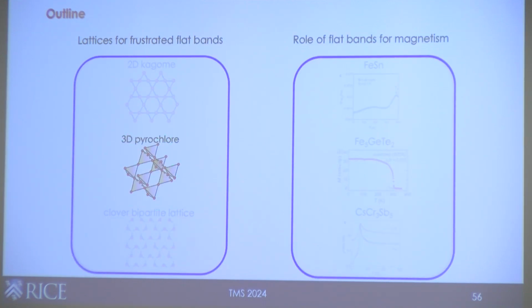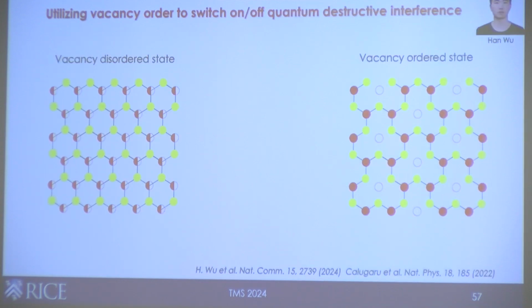So in 3D, we can look at pyrochlore. I want to show you one more that is an interesting and very different way of constructing flat bands in bulk. The difference is that in the previous two examples I showed you, these are fully stoichiometric compounds. You can calculate everything and look at the destructive interference. But there's one more degree of freedom that we can actually utilize to make even more types of these frustrated lattices, and that is the degree introduced by vacancies. This one we happened upon accidentally, but it turned out to be interesting to look at.